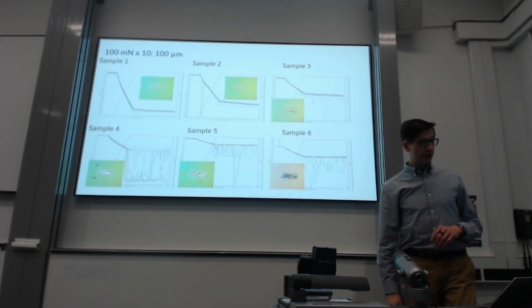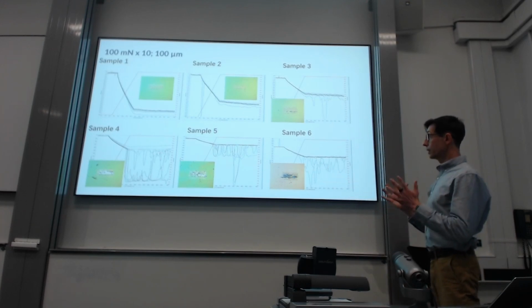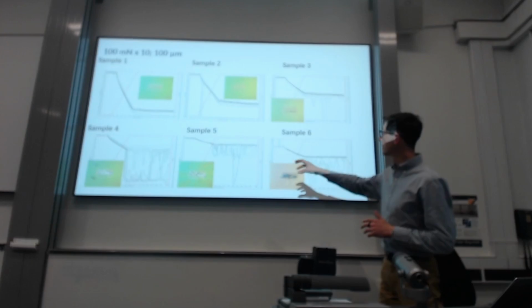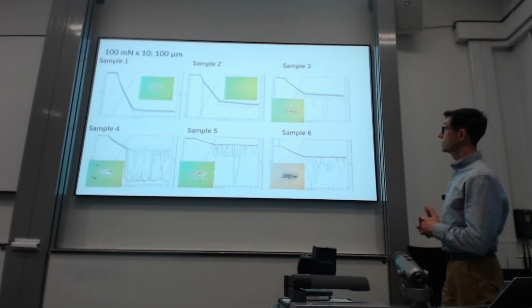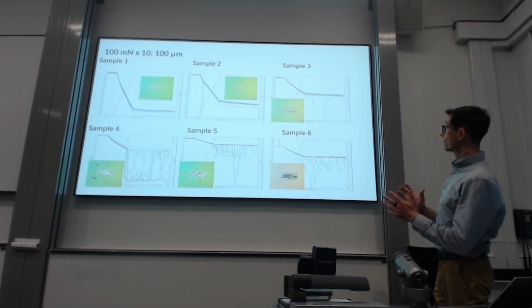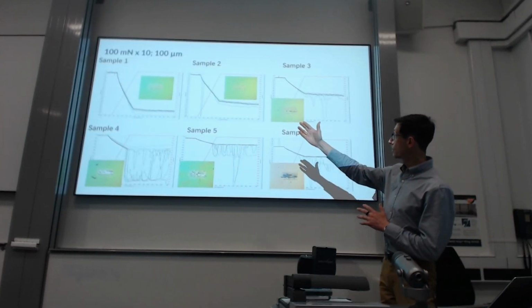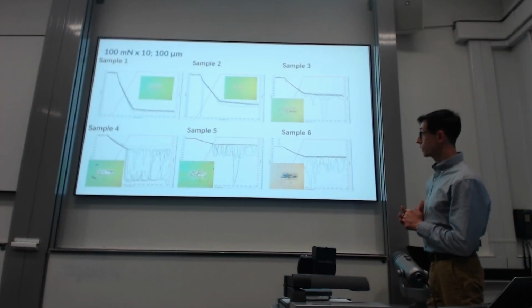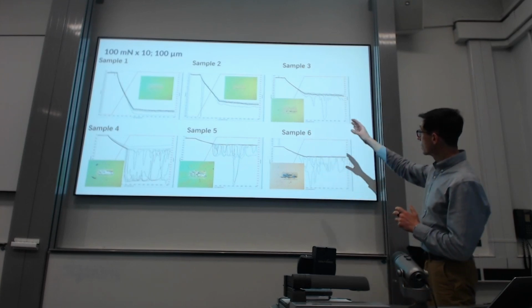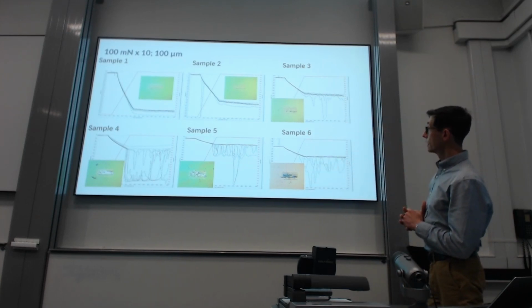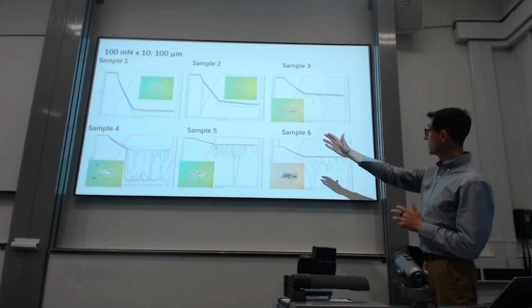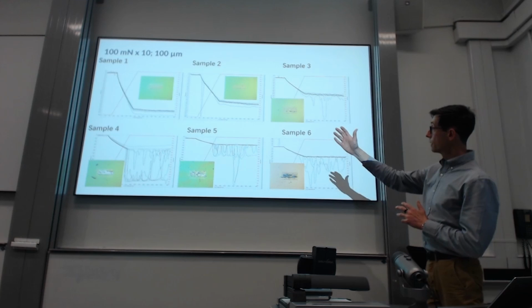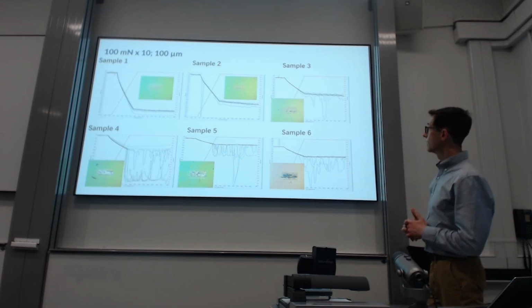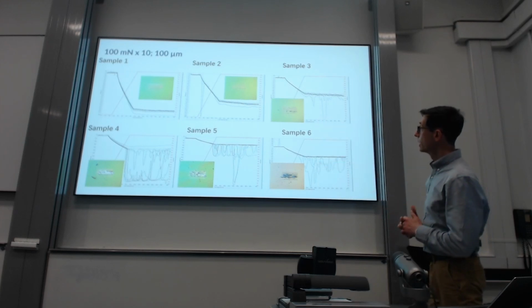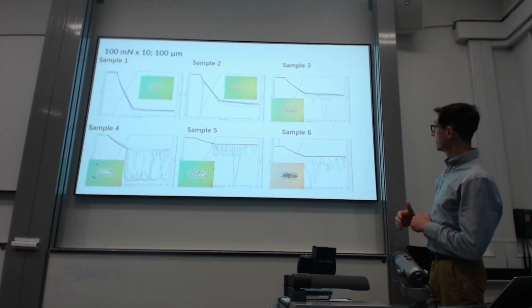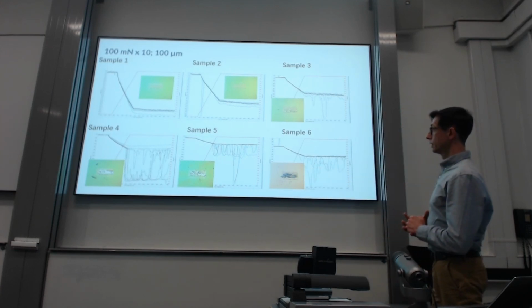So 4 samples, 4 cases, 3 annealing temperatures, so 300, 600, 900. First row is vacuum, second row is air. Very quickly we can see samples 1 to 3 have much less damage than samples 4, 5, and then 6. And perhaps in terms of temperature also there's some variation, with less damage on the lower temperature side than the higher temperature side. The optical images also confirm that, and we can see sample 1 has less damage than sample 3, and vacuum much less damage than air down there.